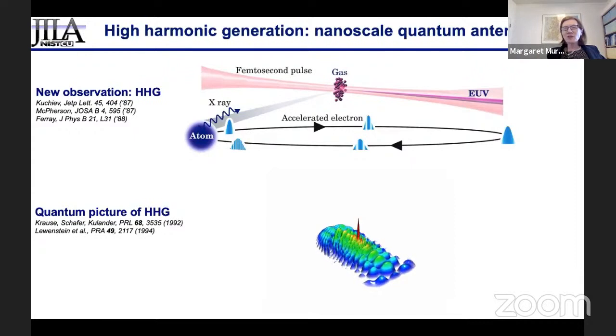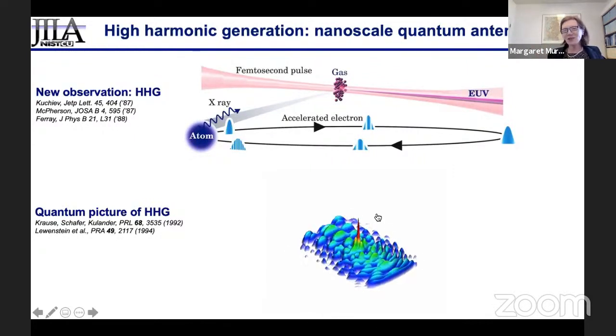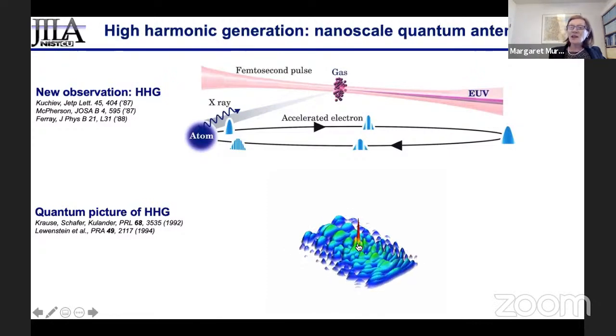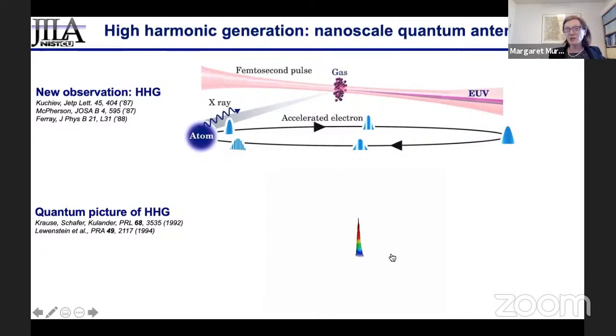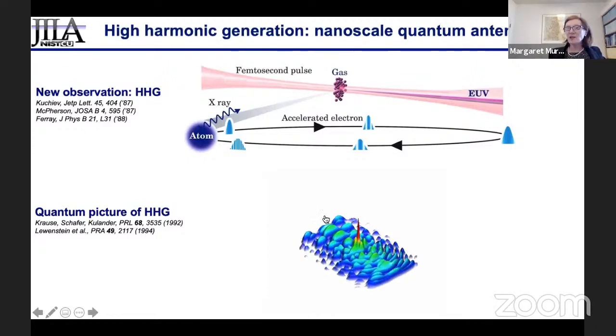you could think about harmonic generation as a sort of Bremsstrahlung-like radiation, but the quantum picture is shown here in this movie at the bottom, where essentially one starts with a 2D representation of an electron, let's say in the ground state of hydrogen. When the laser field irradiates the atom, it drives tunnel ionization, and that sculpts this very beautiful spatially modulated electron wave function, and a corresponding very rapidly changing dipole moment. So although we're driving the electron wave function at the fundamental frequency of the femtosecond laser driver, the rapidly changing wave function in time gives us a dipole moment that has very high order frequencies.